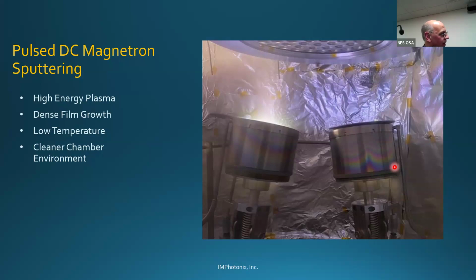I need to mention that also. In addition, because the energy is a lot higher than regular physical vapor deposition, you get denser film growth. You can do it at low temperature. And also the chamber does not have to be cleaned as often. You're restricted to just the area between the gun and the substrates where there's material, and the chamber will pump quicker and to lower base vacuums.